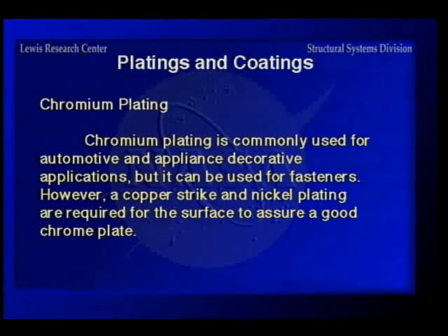Now, moving on to chromium plating. Chromium plating, of course, as you all know, is used for automotive and appliance decoration in very thin coats, but it can be used for fasteners. As I mentioned earlier, it's used for coating fasteners for landing gear, this type of thing, where you require super high-strength fasteners or components, and so you can't use something else like stainless steel, so you go to the very high-strength carbon steel, alloy steel, and then you chrome plate it.